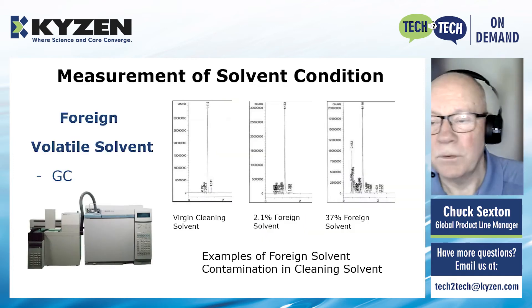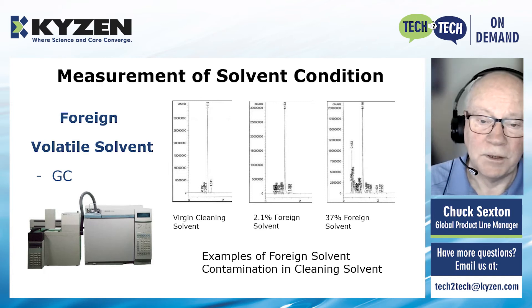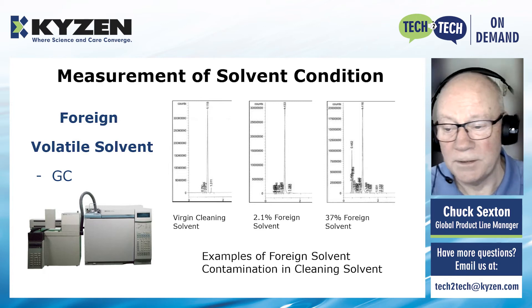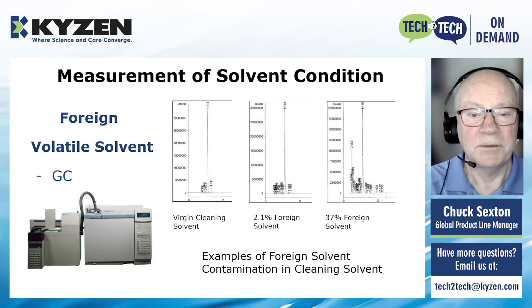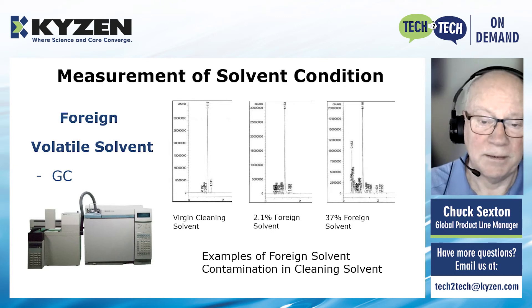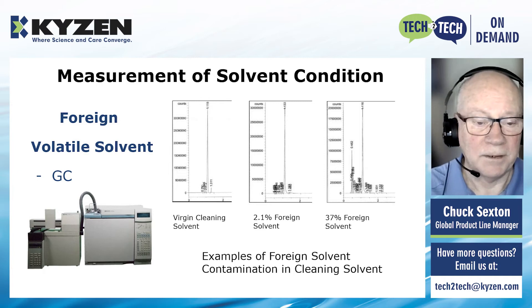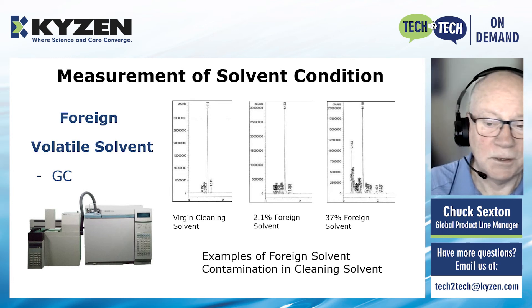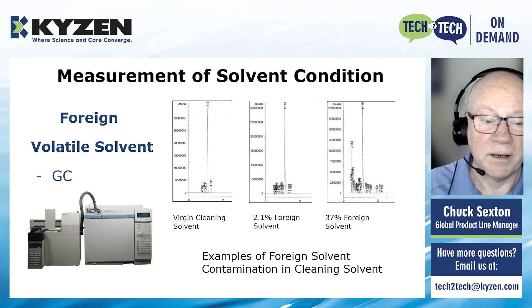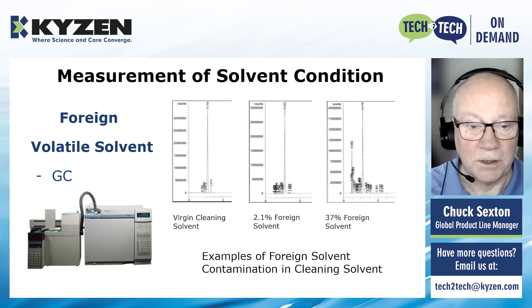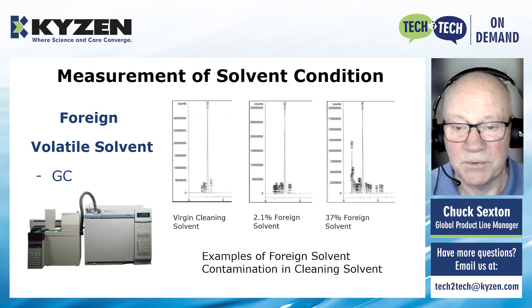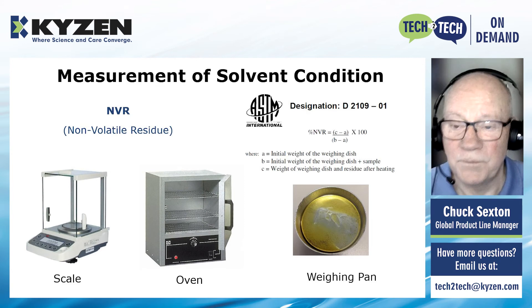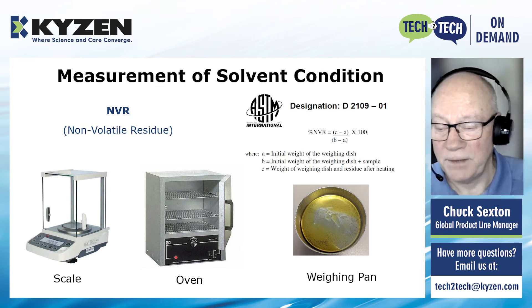Foreign solvent contamination is very important for many solvents. A lot of companies will do pre-cleaning in solvents like isopropanol, for example. Those solvents get into our cleaning solvent and contaminate it, sometimes changing its ability to clean contaminants such as flux from your components. We measure this by GC, or gas chromatography. The chart on the left shows the virgin solvent and the two on the right show different levels of foreign solvent buildup. This is something we can help you stay on top of, and it is important for end of bath life measurement.